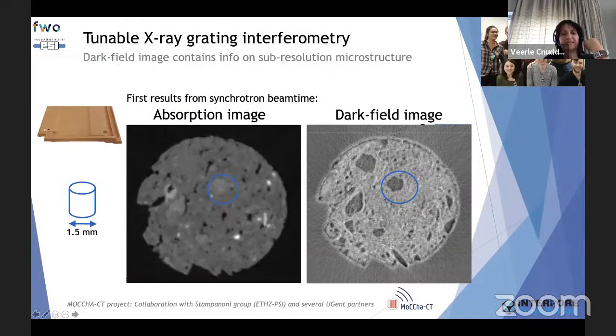So we did experiments last year where we took an absorption and a dark field image. This is a nice example, because you see something which looks like a grain. The question could be, is this a specific grain containing microporosity, or is this a solid material with no microporosity? Based on the dark field images, we can say there are no micropores here, giving no signal. Similar for this area, for instance. But based on the absorption image alone, you are not able to identify this.